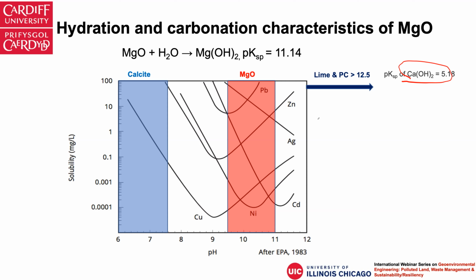orders of magnitude lower. And in terms of the equilibrium pH, commercial magnesia usually gives us an equilibrium pH between 9.5 and 11.5. If you look at this figure, you can see this metal hydroxide solubility graph. You can see that the pH range is almost optimum for precipitating many of the heavy metals. But if you're using lime and PC, because of the supersaturated calcium hydroxide, you actually have a much higher pore water pH, usually over 12.5. That will cause the redissolution of many heavy metals like lead, zinc and cadmium. So it will sometimes cause problems when using PC for soil stabilization and solidification.